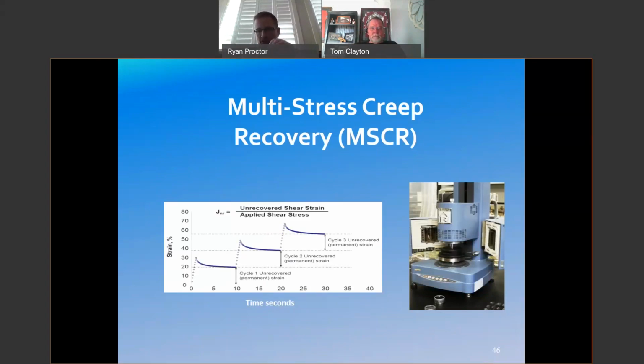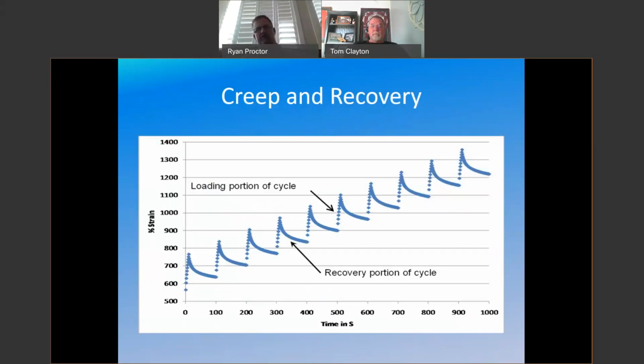But what you do is, if you think back to that DSR, where that spindle's rotating on the top, you put a stress on it, you let it relax. You put a stress on it, you let it relax. And you're measuring how much it's relaxing. So if you had a really, really elastic polymer or binder, it's going to relax a lot further than if you have something rigid. So that's what the test looks like. You can see where you add the stress, that it goes up, and when it relaxes, it goes back down.